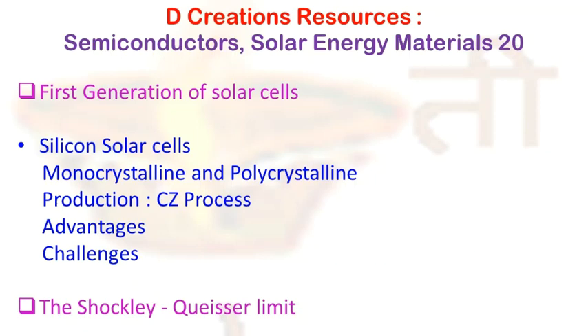Multicrystalline silicon blocks, on the other hand, are produced through melting high purity silicon and crystallizing it in a big crucible by directional solidification process. There is no reference crystal orientation in this process, as in the CZ process, and therefore silicon material with different orientations is produced. The most commonly used base materials for solar cells are p-type silicon substrates, which are doped with boron, and n-type silicon substrates. Now there are challenges such that the doping has to be uniform along the silicon block. So that is an important challenge one has to address.